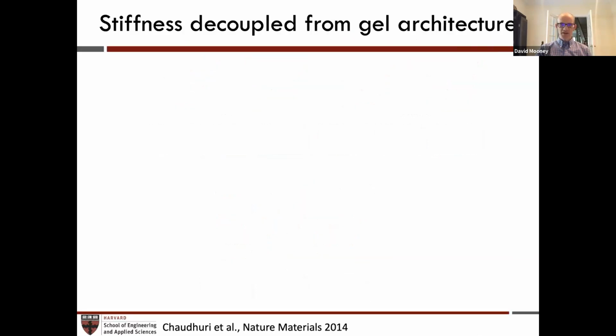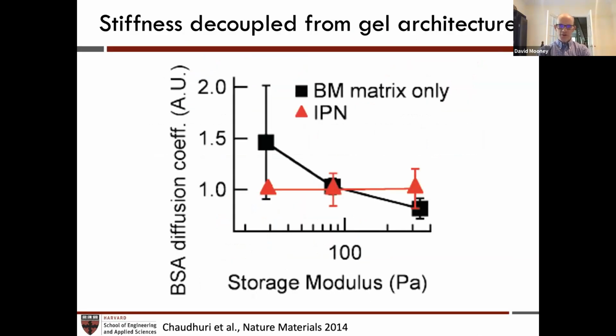And just to give you a little sense of this, here's the effective diffusion coefficient of a macromolecule, BSA, as one takes a gel made out of basement membrane materials like laminin and varies the storage modulus, and you can see the diffusion coefficient is significantly altered. But when we use alginate gels to control the mechanical properties, we can keep the transport properties largely identical across a broad range of mechanics.